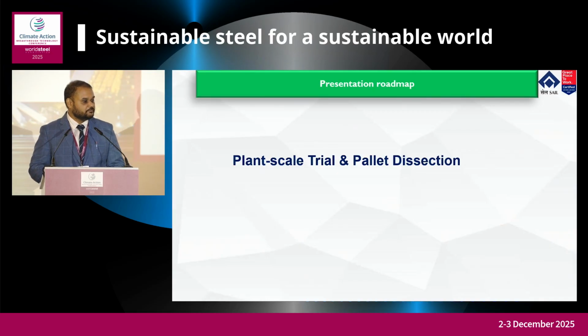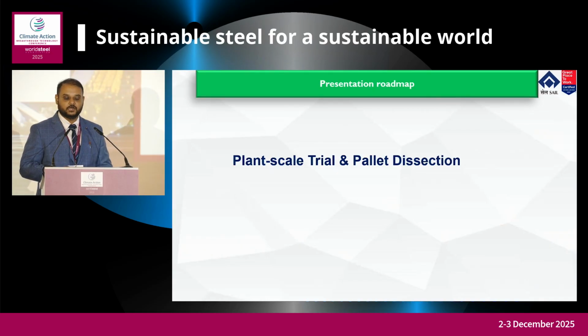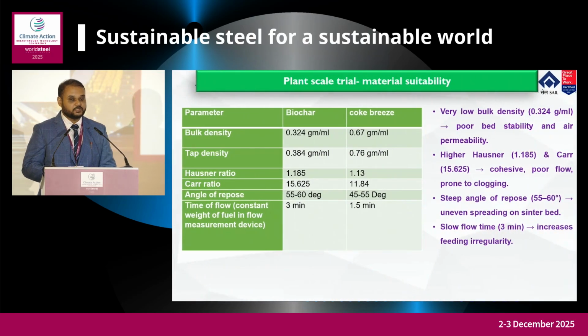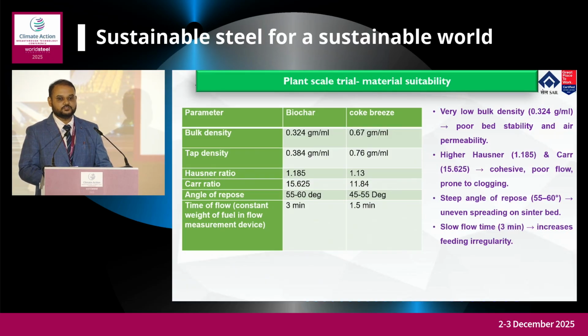Now the plant scale trial: we have conducted a full-fledged plant scale trial at Durgapur Steel Plant. Before going to industrial scale, we tested some physical properties, like flowability and bulk density, and other properties for handling these biochars, using the Hausner ratio, Carr ratio and flowability test standards, because our systems were designed for handling coke breeze, and biochar has some properties different from coke breeze. So we had to suitably modify our charging devices, our weigh feeders, and our measurement devices to suit the percentage replacement of biochar.